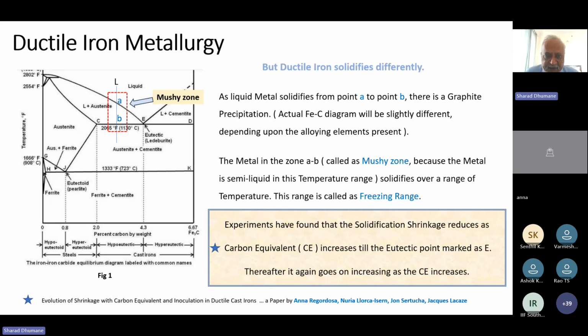This is all experimental data. Experiments have found that solidification shrinkage reduces. Solidification shrinkage means the reduction in volume between liquid and solid. It reduces as carbon equivalent increases. As carbon equivalent increases from this point towards this, the shrinkage decreases. That is experimental data, and it has become a guideline for us to decide what carbon equivalent we should operate at to have reduced solidification shrinkage. It helps us decide our composition grade to match the property requirement and also the requirements of feeding. We want a composition where the shrinkage requirements are quite low and we are still able to meet the properties.